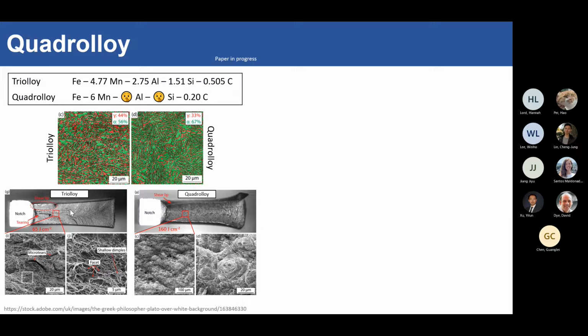And all the results, all the tensile tests I've been presenting, those were quasi-static. But remember, these steels we wanted for energy absorption, so we need them to be tough. And at the end of my PhD, I finally actually did a toughness measurement using a Charpy test. So you can see Quadrolloy, we have a very nice dimple surface here, very, very deep dimples, and that's representative of ductile failure. And that's why you've got very high energy absorption.